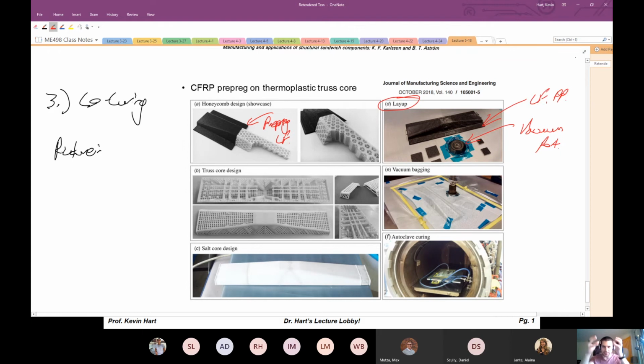And so what happens is you put this entire layup inside of this vacuum bag. All this white is bleeder cloth. Here, this yellow is vacuum tape. And it's all surrounded by what would be the vacuum bag. This goes to an autoclave and gets connected to the vacuum. So you see the vacuum line being connected to the vacuum port, and it's going to suck all the air out and compress the atmospheric pressure down onto that truss structure.